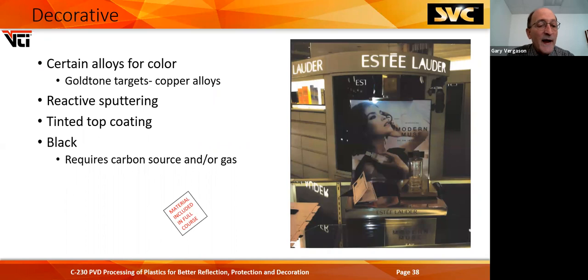Decorative coatings are all over the map. There are many gold-tone targets that they make, different copper and aluminum alloys to give you a whole range of different golds. You can do it with reactive sputtering, bringing in carbon, oxygen, or nitrogen-bearing gases to get different colors and materials. You can paint, tint, or top coat. The most requested one is black. Everybody wants black, and that's one of the worst ones to get to. It requires a carbon source someplace.